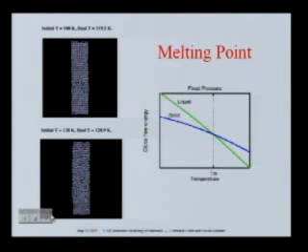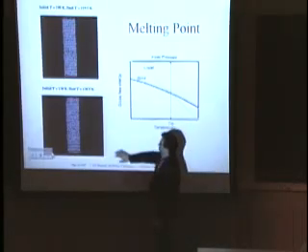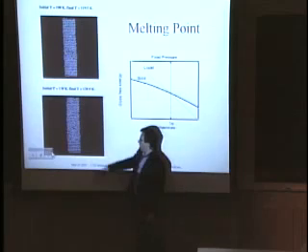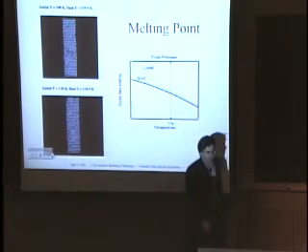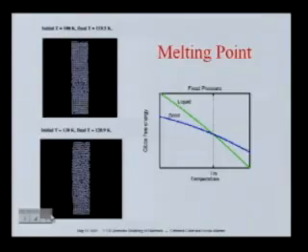The caveat in doing this kind of simulation is that it is still very expensive to do ab initio. You usually need at least 400 or 500 atoms to do such a simulation and to kill the finite size effects. And this is even now borderline for what we can do, even for the simplest elements. There is another approach that I wanted to introduce first, and it is the one in which we explicitly determine the Gibbs free energy.